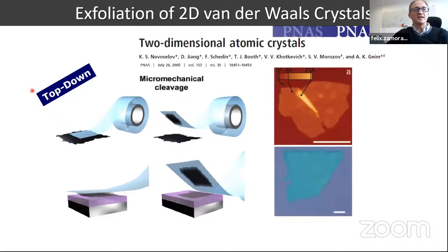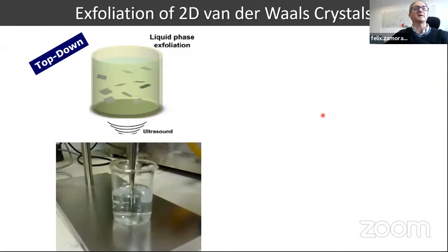But in any case, you can transfer what you have on the tape onto several substrates and analyze the result by using different kinds of microscopy. For instance, sometimes optical microscopy or eventually AFM, atomic force microscopy. Starting from that, you can analyze not only morphologies, but also physical properties, and eventually you can end up with fundamental devices.